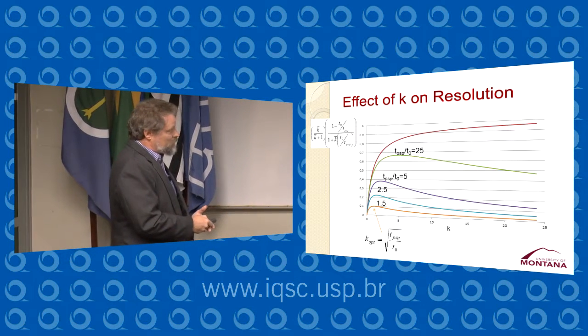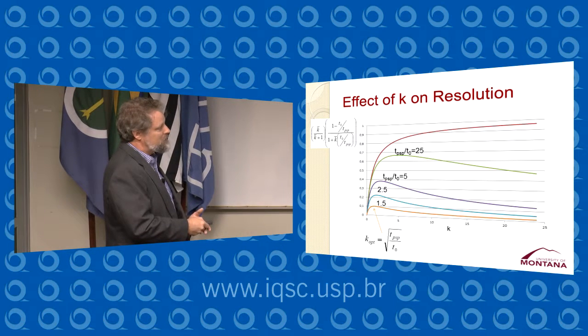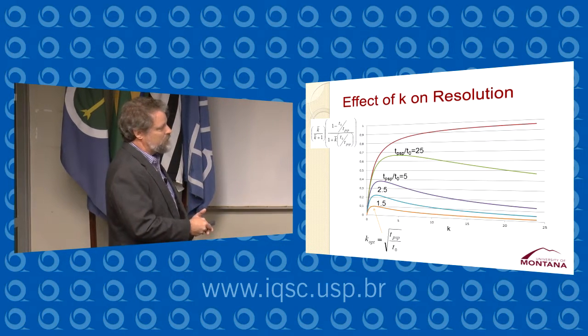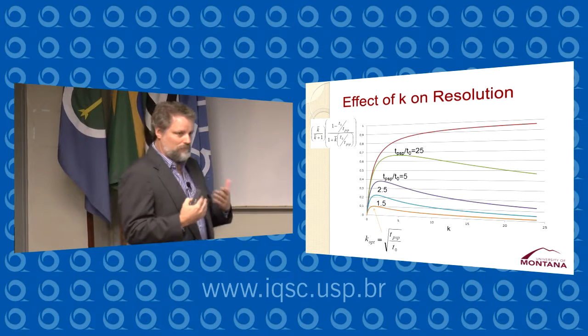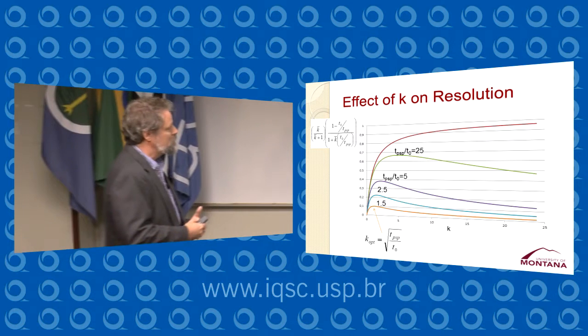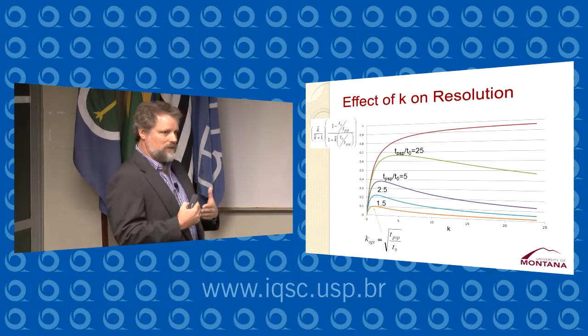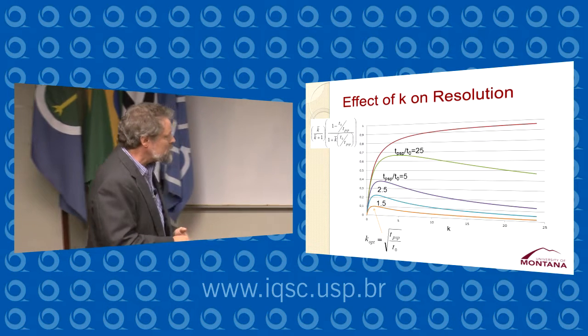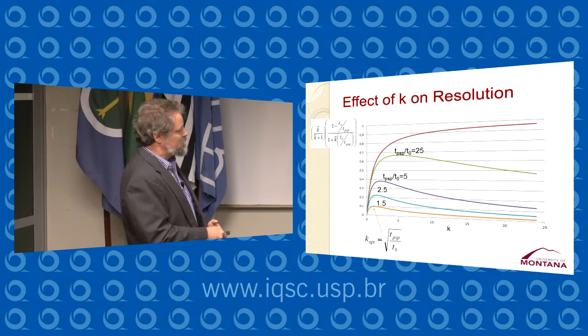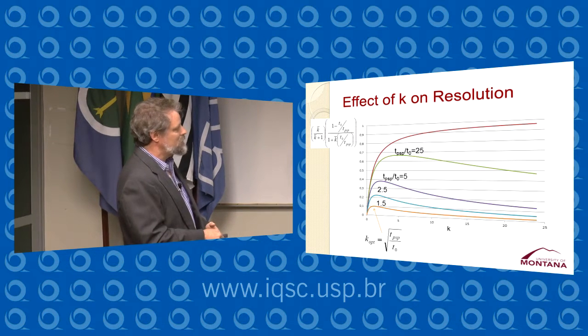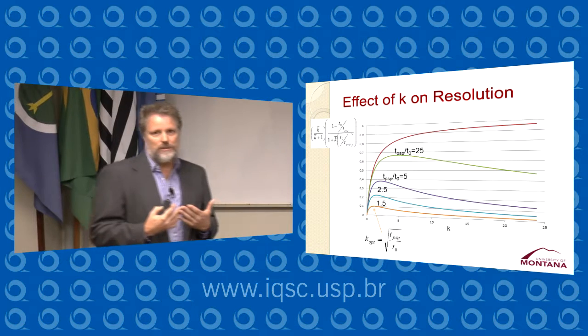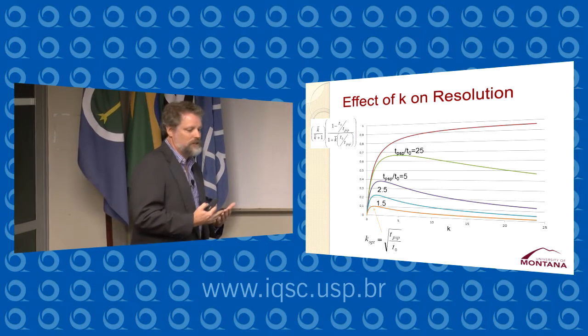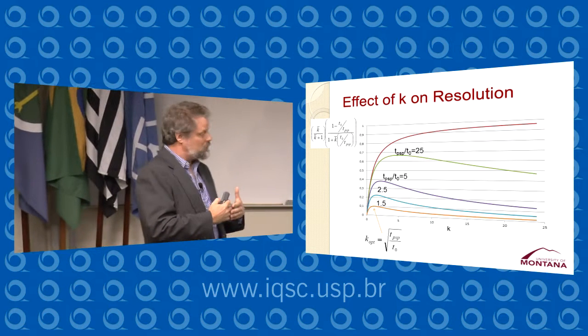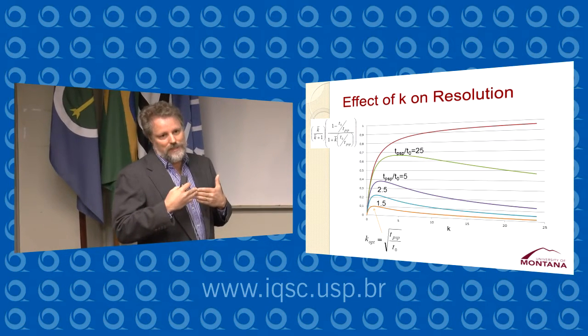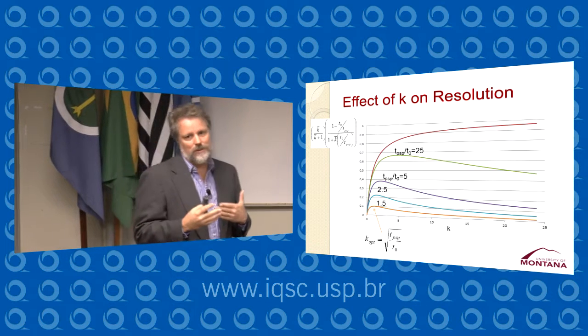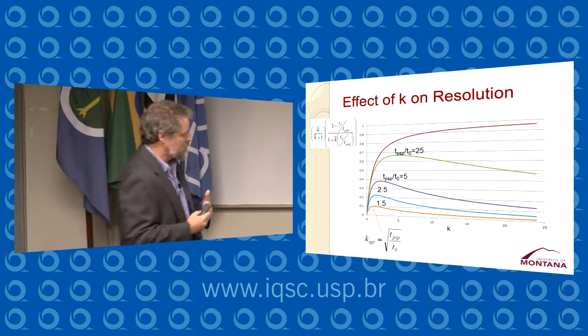We want the separation efficiency to be as high as possible, which means minimizing the current and making sure that we have fast mass transfer and also a relatively monodisperse pseudostationary phase. And we have to be concerned about the ability of the pseudostationary phase to solvate our analytes. We want high separation selectivity, pure materials, and we have to worry about the extent to which the pseudostationary phase will interfere with detection. Because unlike conventional chromatography, in this technique, the pseudostationary phase migrates right through the detector. So we have to be concerned about the effect it will have on the signal from the detector.